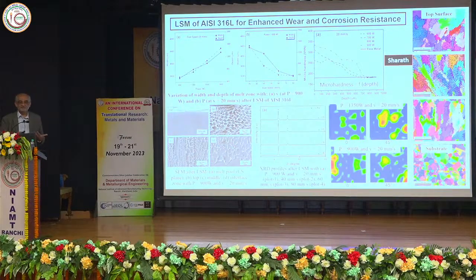Stainless steel is meant for stainless activity, for corrosion resistance. So if you create a top surface where the boundaries are actually less than a degree or just about a degree, then formation of galvanic cell is minimized, and the corrosion damage is also minimized.